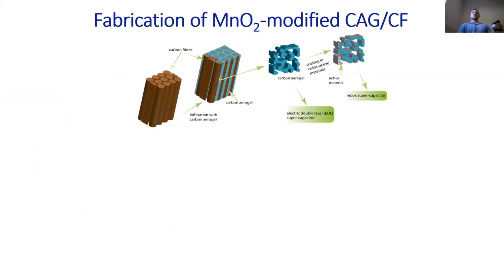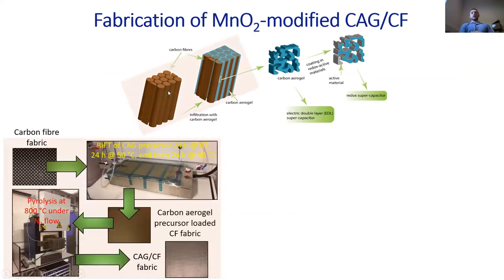So the fabrication of manganese oxide decorated carbon aerogel carbon fiber composites is actually a multi-step process, which includes different experimental steps, starting from infusion, a vacuum-assisted resin infusion procedure, to introduce carbon aerogel organic salt precursor inside of the carbon fibers. This procedure is actually quite a well-established route for introducing epoxy resin into conventional structural composites. So it's well compatible for our application.